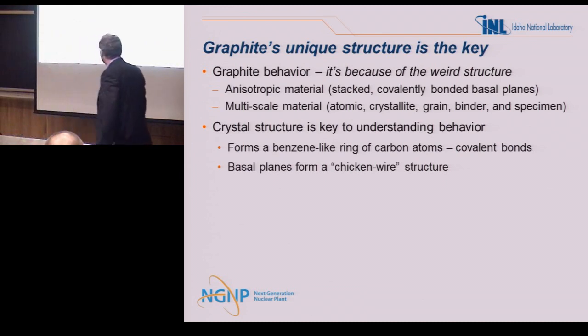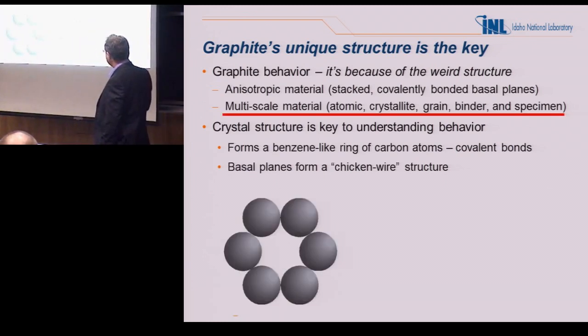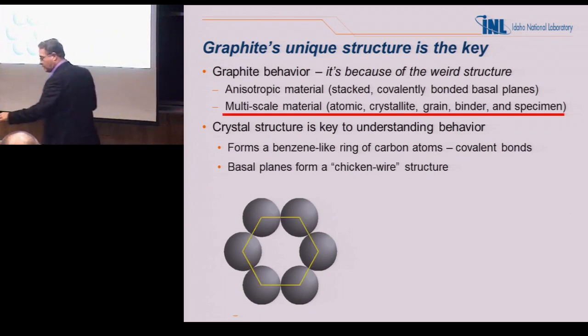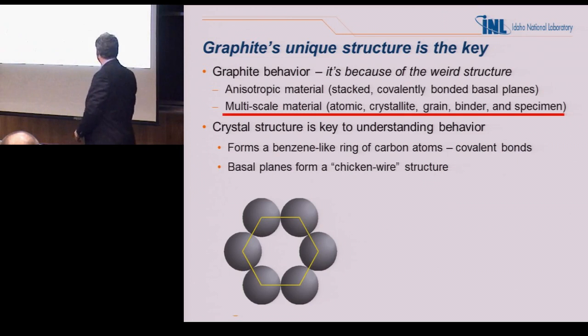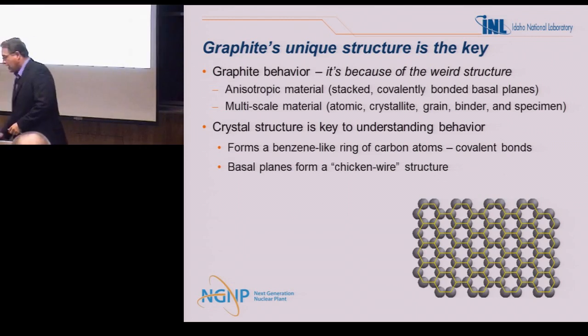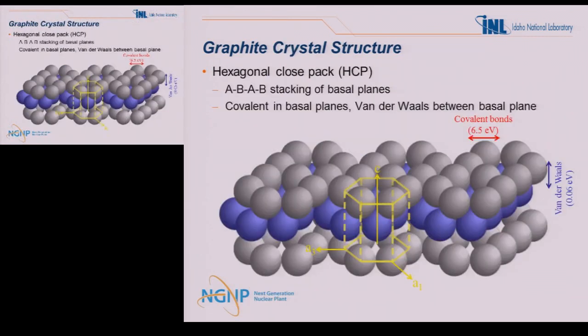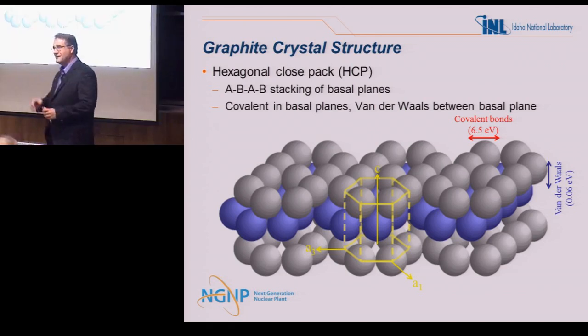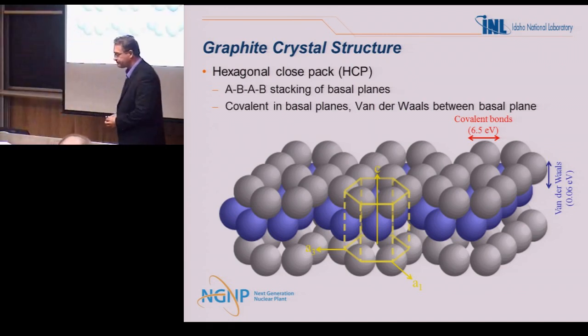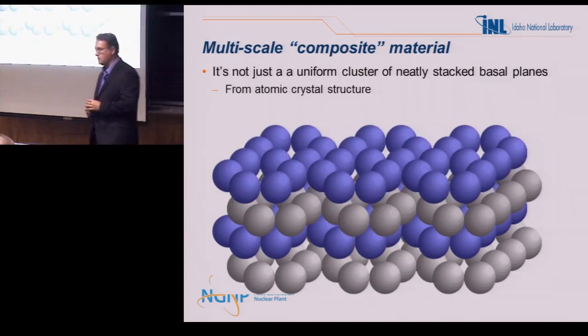Okay, that starts off with this benzene-like ring, which we then form into a hexagonal ring, which then comes into this chicken wire type basal plane, if you will, or graphene type plane, and then they stack these things up, AB structure, and lo and behold, you repeat that over and over again, and voila, you have your graphene structure and your graphite crystal structure, HCP crystal structure. Again, very strong covalent bonds in this direction, very weak bonds in this direction. Key to understanding what's going on at the atomic level, all right?